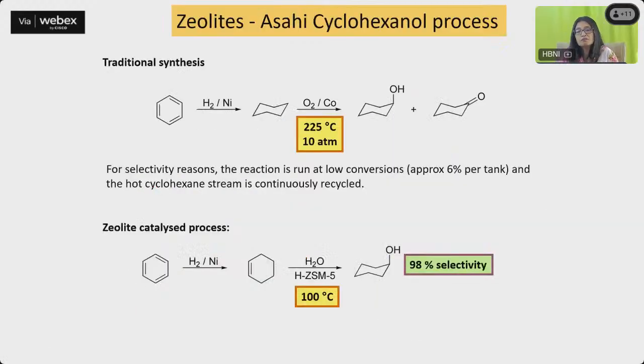Let's look into a few reactions where zeolites are used as a catalyst. In the cyclohexanol synthesis process, you have this particular precursor, and you do a hydrogenation reaction in the presence of nickel. Then you process the product again with oxygen and cobalt, and you get a mixture of the ketone and cyclohexanol. This was the traditional synthesis, where nickel and cobalt were used as catalysts. But look at the conditions: 225 degrees centigrade at around 10 atmospheres pressure.